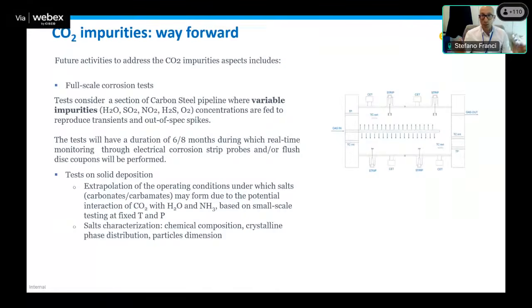So this is going to be a full scale, and the duration is pretty long, from 6 to 8 months, and we are going to exceed the limits, with all the variables, water, SO2, NO2, and so on, and see whether the monitoring system is suitable. And at the end of the 6 months, we want to open the pipe and check inside the damage which was caused by any acid dropping out.